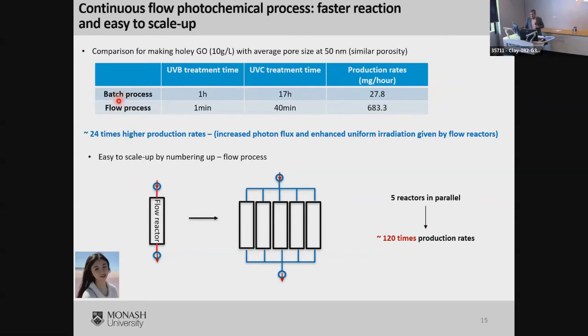So the thing we learned from this work was that in a batch process, we had a production rate of over 27.8 milligram per hour of 50 nanometer holey graphene at a concentration of 10 grams per liter. Whereas when you do the flow process, you can produce about 683 milligram per hour, about 24 times higher production rates. And this happens because we have an increased photon flux and more uniform radiation in the flow reactors. And scaling up is relatively easy.